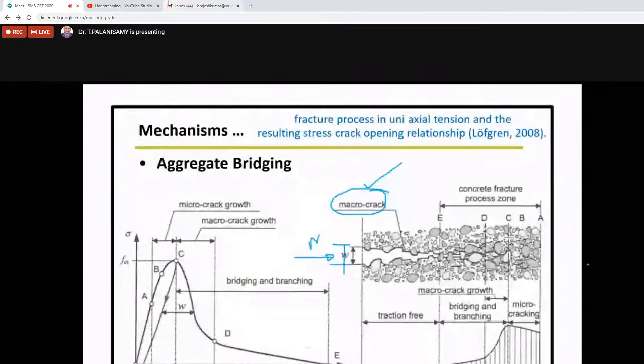What will happen is that the crack moves in this direction, for example, and we have some aggregate. This aggregate acts as a bridging of the crack. That mechanism is called the aggregate bridging mechanism. It also acts as a bridging mechanism in fiber reinforced concrete. Some research scholars may work on this point.